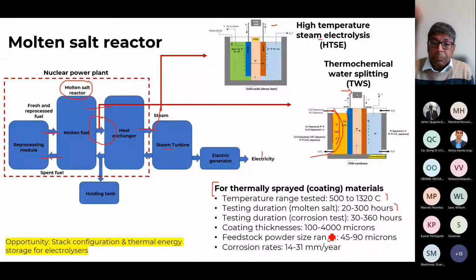The coating thickness in thermal spray is normally 300 micron. As low as you can go is 100 micron, but a few have also manufactured coatings of about 4 millimeter. And I'll show you later that higher thickness is not a good idea. And if you're manufacturing coating, typical powder sizes are about 45 to 90 micron. And if you do corrosion analysis, the corrosion rate they have reported is between 14 and 31 mm per year.